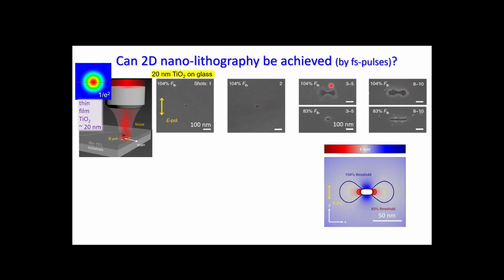dipole scattering, it would be a similar pattern. Yeah, so the polarization of light is the electrical field oscillating vertically, and we see the scattering of light. But what is interesting is that once we have this nanohole ablated, we can reduce the pulse energy by 20%. And then if we are not scanning, we're just irradiating the same spot, we see that it's evolving as a line, which is not getting wider. And numerical modeling kind of predicts this. This white part is actually blocking intensity here, but it's also marking what kind of structure was modeled here.